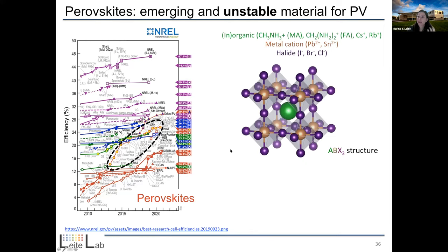However, they're very unstable. These metal halide perovskites are a mixture of an organic and an inorganic type of material. They have this ABX3 structure. You can see here, color-coded, the large organic molecule, and sometimes a mixture with cations like cesium and rubidium that sit here in the center of this octahedra, and then an overall structure. Then we have the metal cation, usually lead, which is toxic, but I won't get into details on that. They are extremely small, less than what we have in an AA battery. And then we have the halide anion here, iodine or bromine or chlorine.